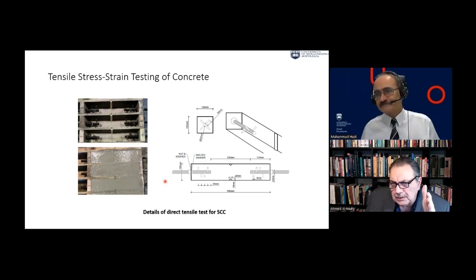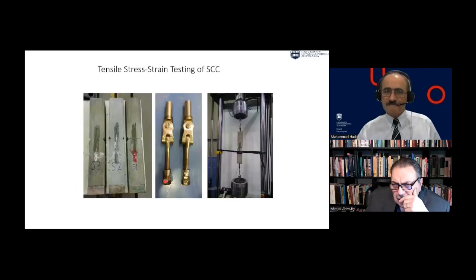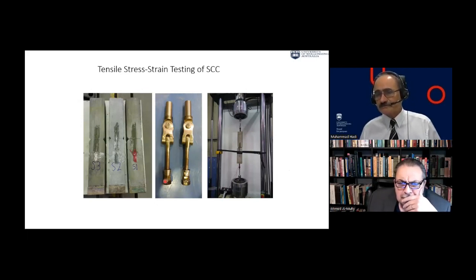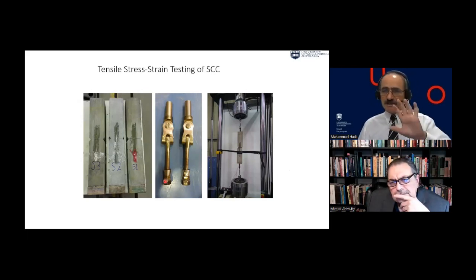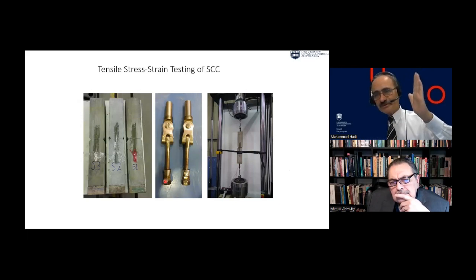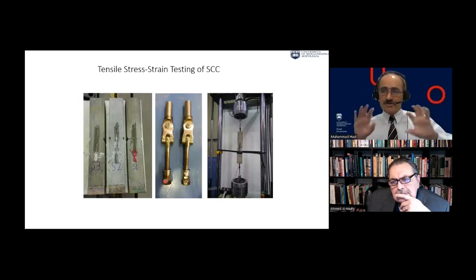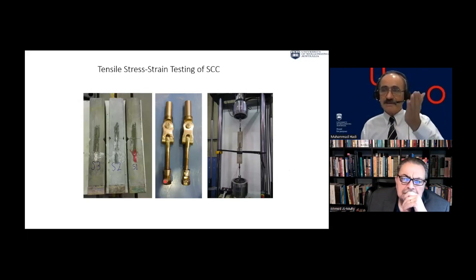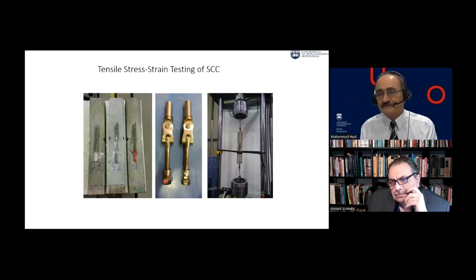I just want to add something. When splitting starts, it happens immediately. There's no time. Of course, we test them under displacement control. I just want to add one thing. We do 7 days, 28 days, first day of testing, last day of testing. Each of those, we do 3 compression samples. But at 28 days, in addition to those 3 samples in compression, we do flexural tests on beams, 4-point bending, and we do splitting, each one of them 3. So we have the proper material testing at 28 days.